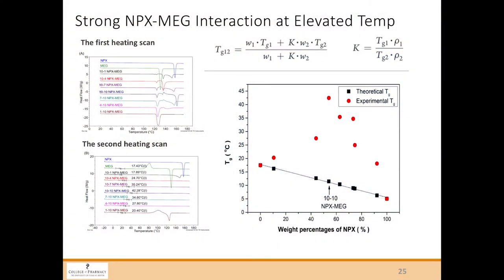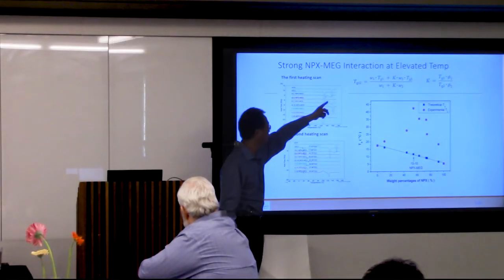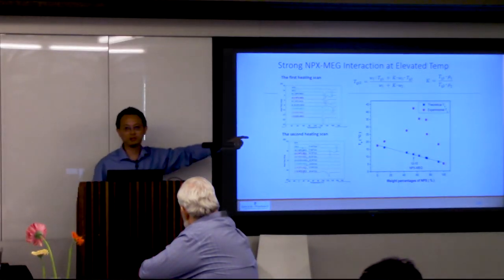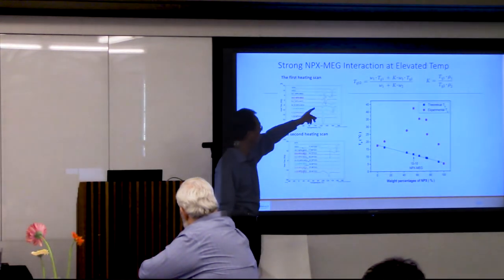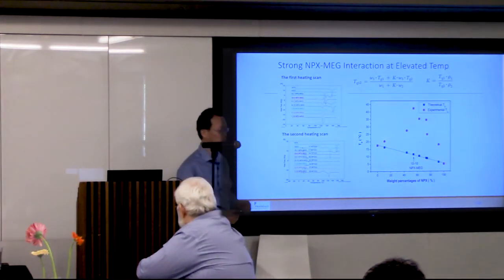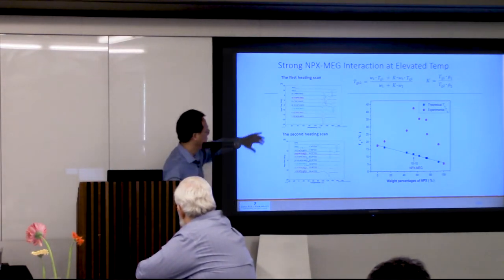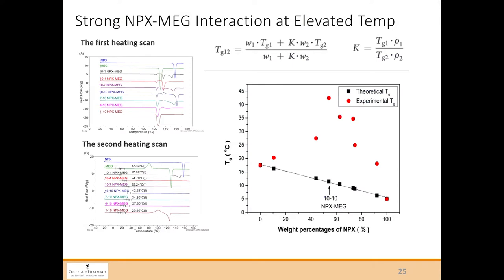What's interesting here is naproxen melts. If you cool it down, in the second heating it melts again, because naproxen crystallizes so quickly. No matter how fast you quench, unless you drop it in liquid nitrogen, it always crystallizes. Look at MEG at its own melting point. Now, similar to the case I discussed earlier, when you mix them together, let's look at this one-to-one molar ratio, there's actually a significant melting point depression as well. Now, for all of those mixtures, when you go through the second heating, they actually do not crystallize. You can actually make an amorphous material.